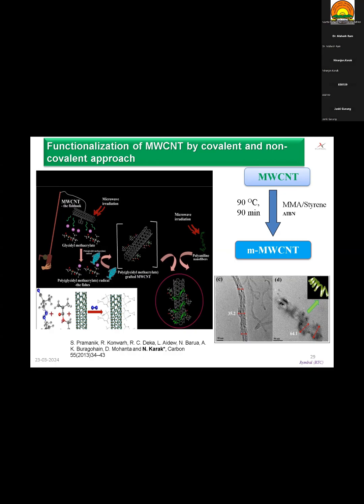Thus, we thought, why not a combination of covalent and non-covalent modification, which we call a hybrid approach, where we can covalently link some functional groups on the surface and non-covalently wrap on the surface of the nanotube. In this process, we get modified carbon nanotube, which can be incorporated into the polymeric system without deteriorating the nanotube performance.